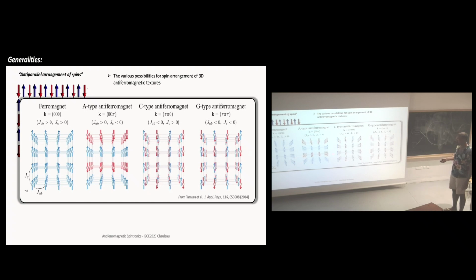you have what you call the A-type antiferromagnet. So basically you have stacks of ferromagnetic layers which are antiparallel. Then there is the C-type antiferromagnet, when two of the neighboring spins this time are antiferromagnetically coupled and one is ferromagnetically coupled. So you have lines of ferromagnetically aligned spins, basically, and then you have these planes, which, if you take the cubic lattice, are in the 110 direction.